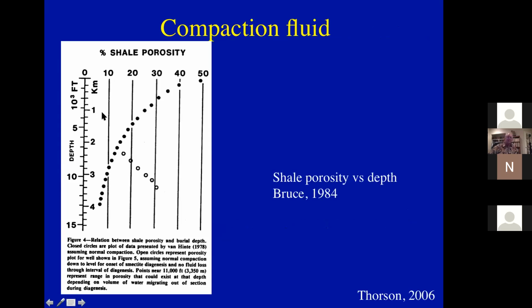Now, when sediments compact, we have this plot of shale porosity, and you can see when it's at the seawater mud interface, it's essentially 50% water, and the amount of water-filled pores drops rapidly. And at 4 kilometers, it's somewhere less than 10% porous. Some basins have a divergent amount of porosity in the shales here, where at a certain depth, just below 2 kilometers, all of a sudden there are shales that have extra water in the pores. In other words, they're overpressured.